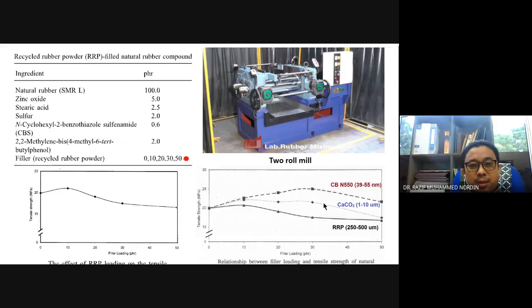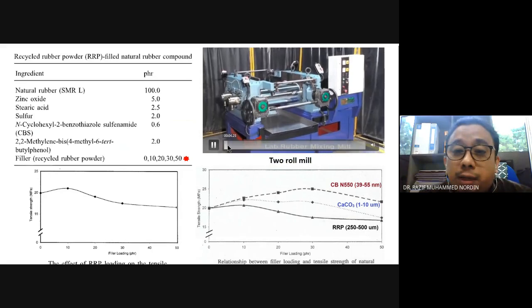For recycled rubber, this is what I did during my master. So this is the formulation for it. To compound rubber, you need to process it within 25 minutes. Over here, there are seven ingredients that you need to mix within 25 minutes. The process is about 300 gram per mixing. The mixing process needs to be done by using your hand, on this two-roll mill. It's a typical two-roll mill.